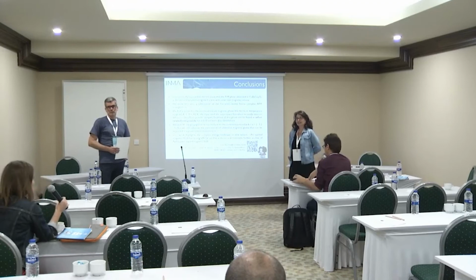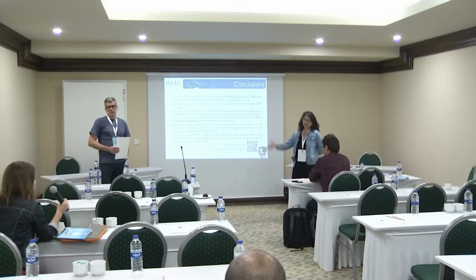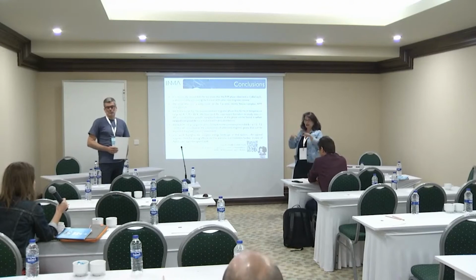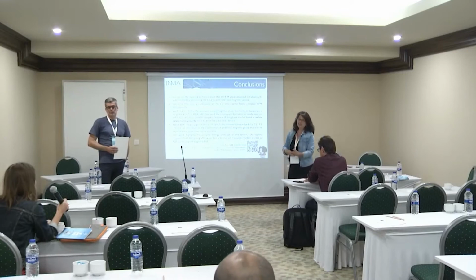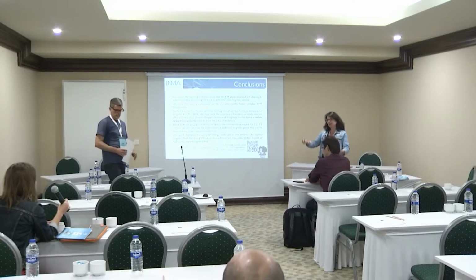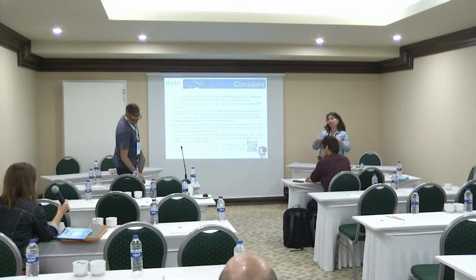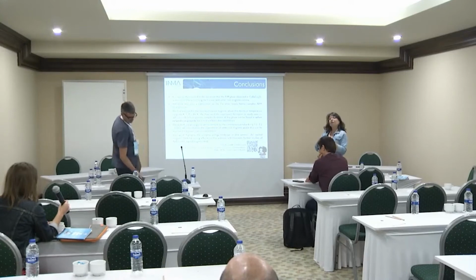You're only thinking about the magnetic part, and I am studying the magnetic part because I'm using neutrons, but the possible origin for this coupling of the increase in polarization that you observe if you measure the dielectric constant, or if you make experiments of polarization, is probably magnetostriction, because, I didn't show it, but the ferrimagnetic phase has a very sharp change in the lattice constants, a stepwise change.